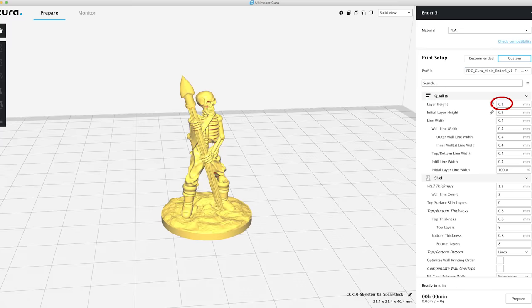Now, if you want to create your own profile or use my settings as a guide for your printer, if you're not using Cura or something, let's walk through these one by one, the things that I've done to get the results that I've shown earlier in the video. In both cases, the lizard men and the skeleton, I'm using 0.1 layer height. And in all honesty, you really don't need to go any thinner than this for a 28 millimeter miniature. I don't notice any increase in detail, and I actually see a decrease in surface quality. I get increased stringing when I go thinner. I see blobs and zits on the side of the model simply from the radiant heat causing prior layers to hit those glass transition points, and it just creates more problems than it's worth. And those miniatures came out wonderfully at 0.1, and it totally eliminates the glass transition point issue for prior layers.